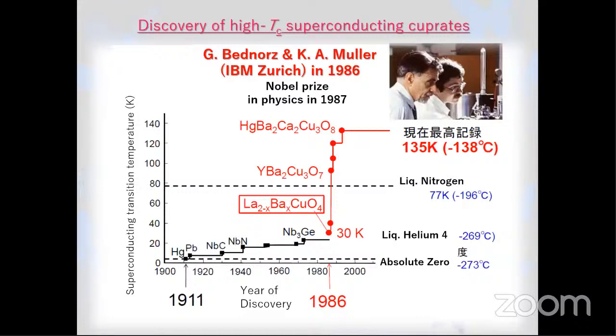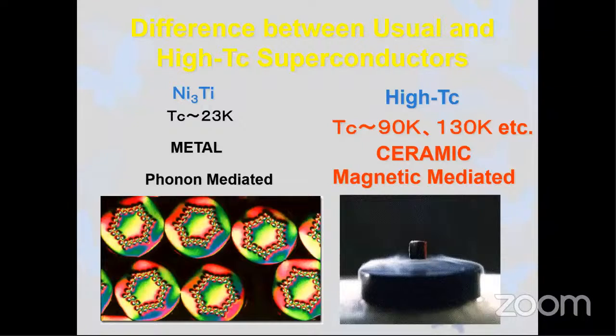So we can think about the application of these materials as industrial devices. The big difference between the normal superconducting state and the high-Tc superconducting state is that high-Tc superconducting materials are ceramics. It's not a metal, it's a ceramic, just like concrete, and this ceramic shows the superconducting state. This is very shocking data. Also, the usual superconductor forms the Cooper pair by using a phonon, but a high-Tc cuprate uses magnetic interaction. So nowadays, the magnetic interaction is the key to discussing how to increase the transition temperature.